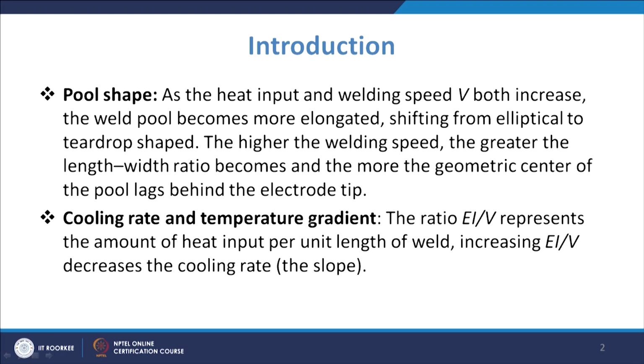So, as the heat input and welding speed V both increase, the weld pool becomes more elongated, shifting from elliptical to teardrop shaped. So, basically as you increase the heat input and welding speed both, initially when your V is less and heat input is also less, then the pool is basically in the form of elliptical, and because you are moving in one direction, you will have an elliptical type of pool. But as the speed is increased, the length width ratio becomes more and more, and the geometric center of the pool lags behind the electrode tip.